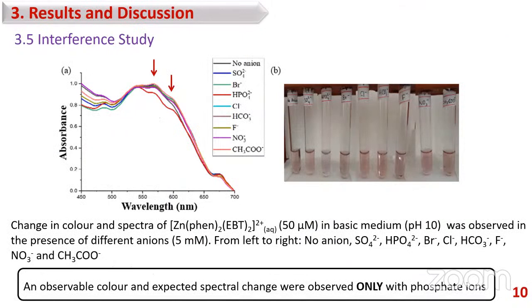At last, an interference study was carried out in order to make sure that none of the anions alter the assay result. Here, the change in color and spectra of zinc phenanthroline EBT complex in the basic medium was observed in the presence of different anions. An observable color change and expected spectral changes were observed only with the phosphate ions. So, we can confirm that phosphate ions are selective and sensitive towards the complex over other anions.